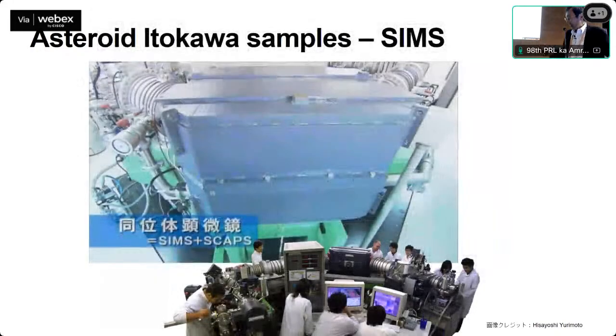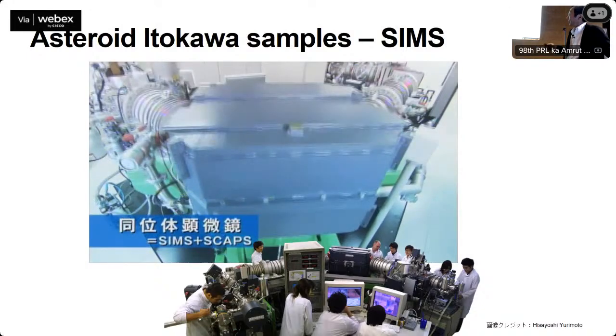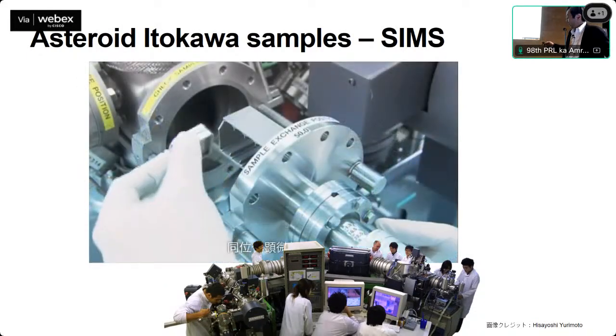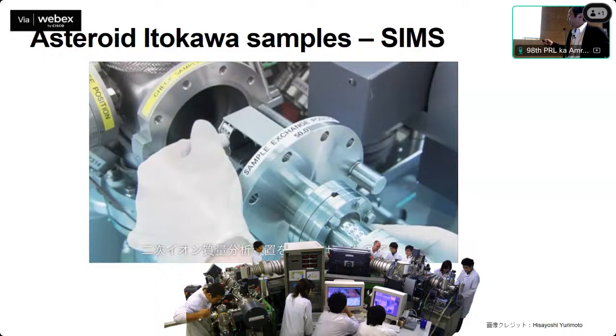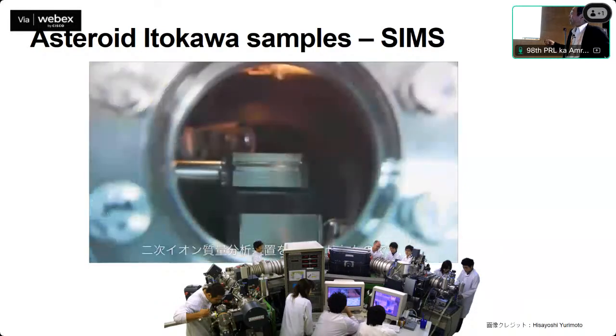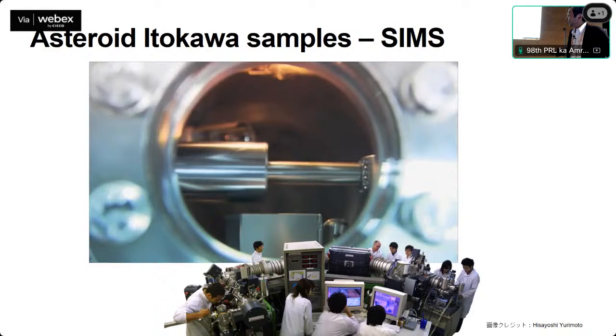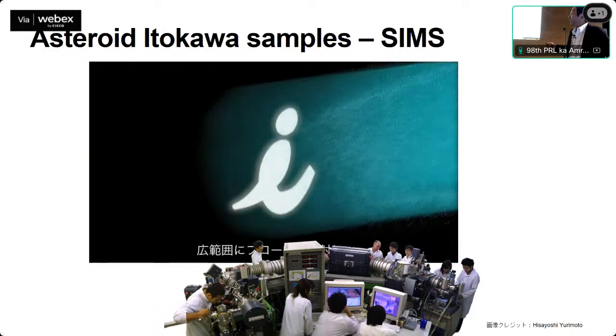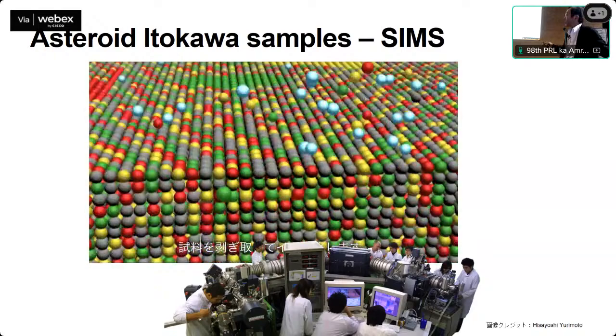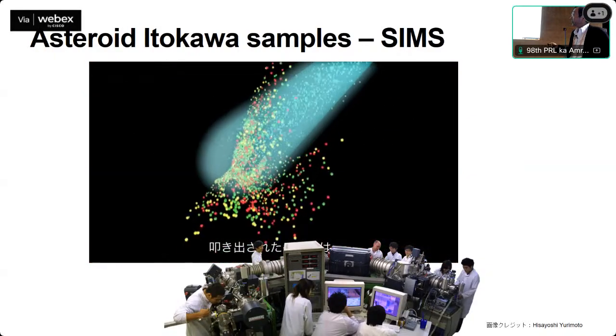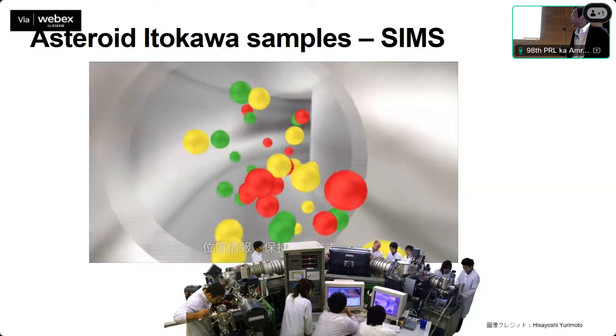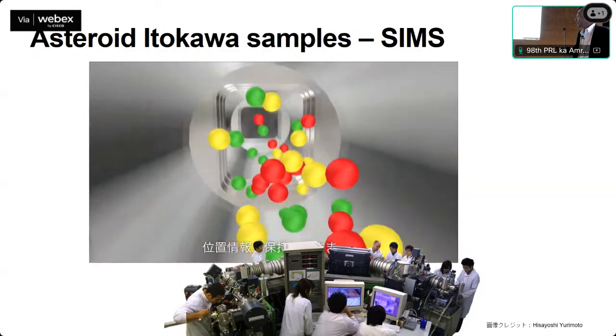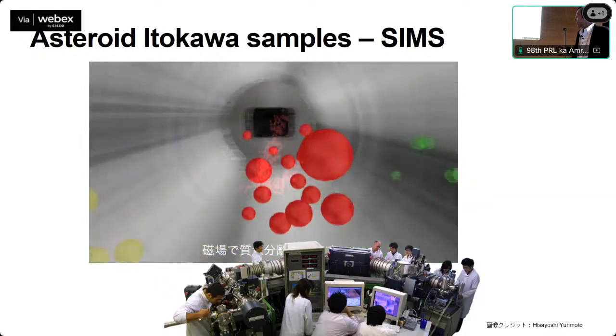So we measure with this kind of instrument. This is a big SIMS. Okay, this big block is a magnet. The sample is installed in the sample chamber here. Then an ion beam is irradiated on the Itokawa surface, the Itokawa samples. So Itokawa atoms are sputtered out and go to the mass spectrometer. And then each of the ions is counted here.